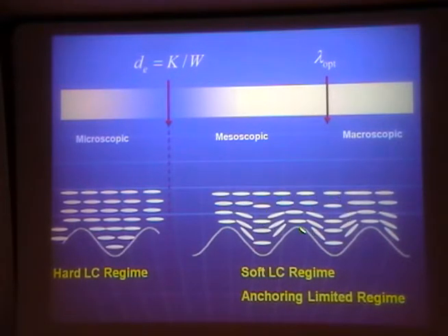Perhaps you already know that Oseen-Frank elasticity can very precisely describe the elastic behavior of liquid crystal alignment. So when the liquid crystal is in contact with whatever restrictive surfaces in terms of morphology, in terms of alignment patterns, then what you get is the distribution of directors that minimizes the total free energy.